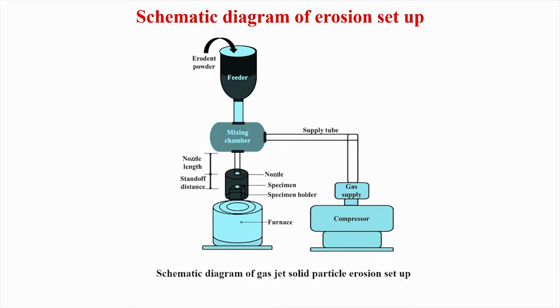Now, having said this, we have done these experiments in a gas jet erosion setup. This is the schematic of the gas jet erosion setup. So, this is the furnace. You have to keep the entire erosion nozzle as well as the specimen holder inside the furnace here. This is the typical nozzle length, this is the standoff distance, and this is the mixing chamber. The mixing chamber is used when you want to use two different erodent powders; you can mix them at an intermediate place, and you can also mix with the gas. Through this gas jet, these erodent particles will be bombarding the material surfaces, while the materials experience very high temperature.